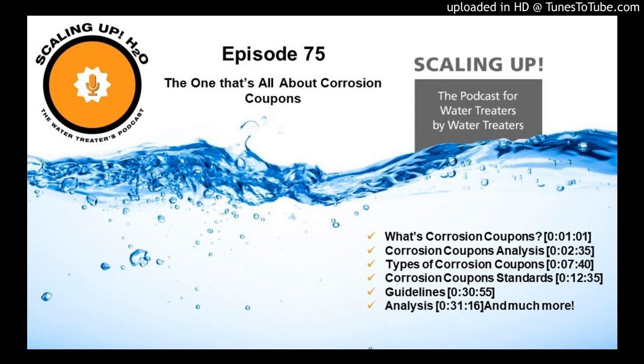So I'll tell you what, I'm going to go into one of the items on the acceptable, non-acceptable list, those standards that I was talking about. So let's talk about mild steel in an evaporative water type system. Anything less than 1 mil per year is considered excellent. Anything that's less than 3, but greater than 1, of course, would be considered very good. And that goes all the way up to anything that's greater than 10 mils per year is unacceptable. And there's a good range, a fair range, and a poor range in between that.